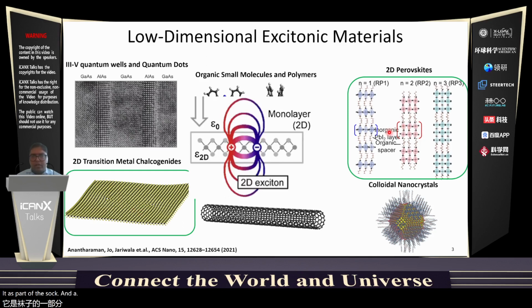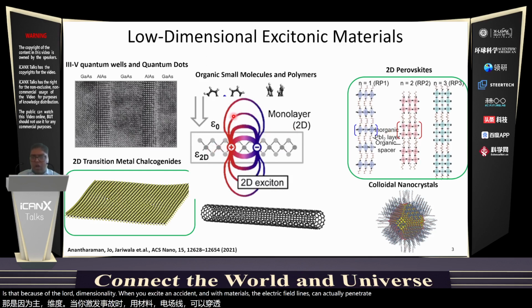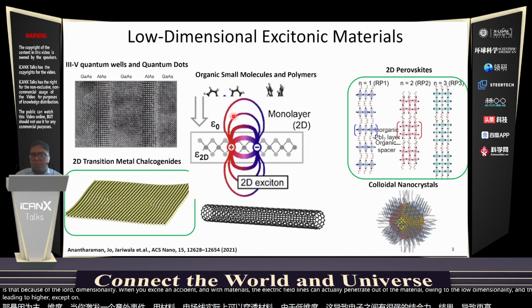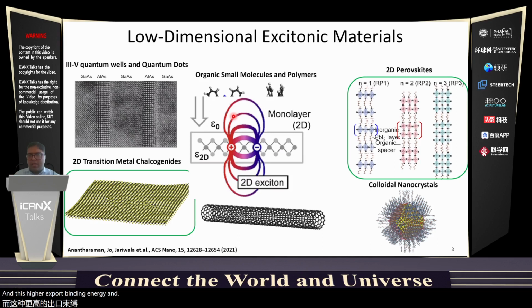One of the things that makes these excitonic materials in low dimensions particularly exciting is that, because of the low dimensionality, when you excite an exciton in these materials, the electric field lines can actually penetrate out of the material. This leads to strong binding forces between the electron and hole, and as a result, higher exciton binding energy. This higher exciton binding energy enables strong excitonic properties even at room temperature. This is something that has always been lacking in bulk or three-dimensional excitonic materials, and therefore this opens up a whole new gamut of applications as well as fundamental science investigations.